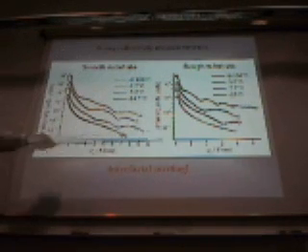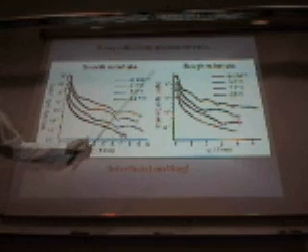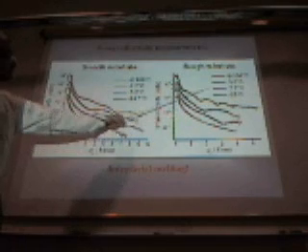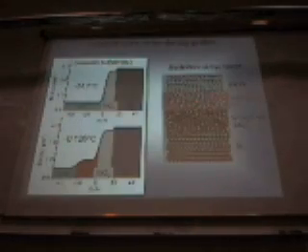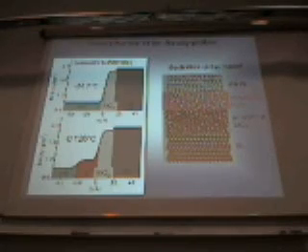If you look from far, it looks pretty much similar, but in detail, it's different. When you look at the fringes, they're different. The onset temperature is roughly the same, but the oscillation strength is a little bit different. And if you go to the same temperatures, the spacing of those fringes is different. So that means morphology seems to have an influence. Now I skip that one.